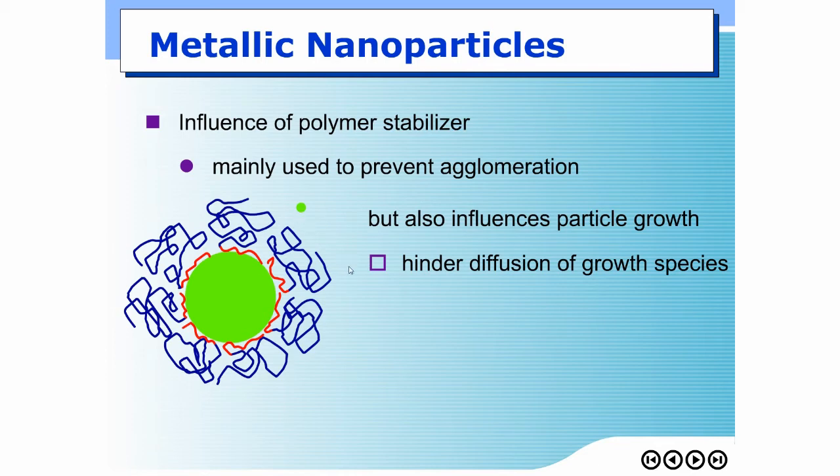The diffusion occurs basically because the concentration around here is higher than the concentration on the surface, and the concentration that I'm talking about is the concentration of growth species in liquid, not in solid. Once growth species reaches the surface of the solid, it will be incorporated onto the solid so that the concentration in liquid is kept small. That difference in concentration drives growth species to the surface.